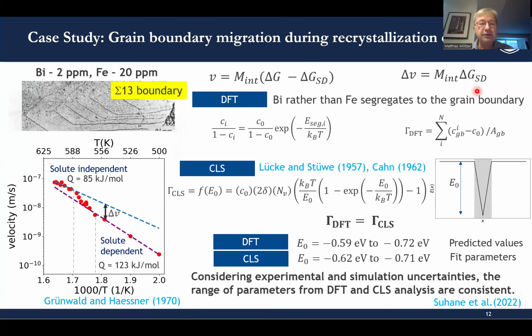And we go back to an experiment that was done by Grünwald and Haessner also half a century ago. They started recrystallization in ultra pure gold that contained bismuth and iron impurities on the ppm level. They found that there's a particular grain boundary that is moving during the recrystallization process. And this is a sigma 13 grain boundary, which we can actually put into a DFT box.